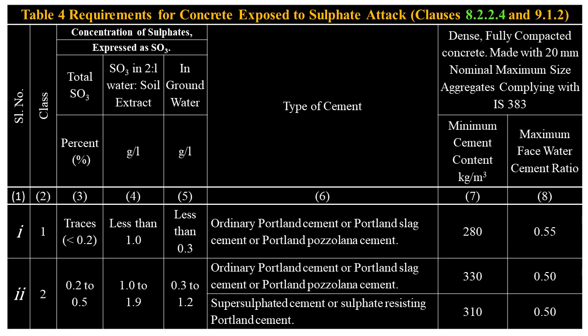Type of cements: supersulfated cement, or sulfate-resisting Portland cement. Minimum cement content, 310 kilograms per cubic meter. Maximum free water cement ratio, 0.5.